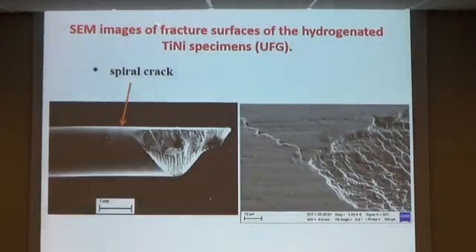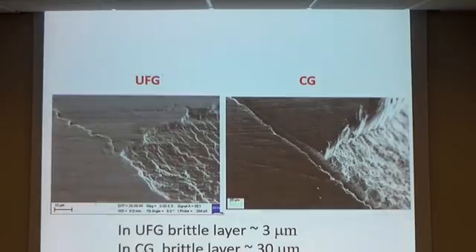It is an image of the fracture surface of hydrogenated titanium nickelide specimens with ultrafine grain structure. Only one spiral crack, also brittle fracture. In ultrafine grain structure, the brittle layer is about 3 microns. In coarse grain structure, the brittle layer is about 30 microns.